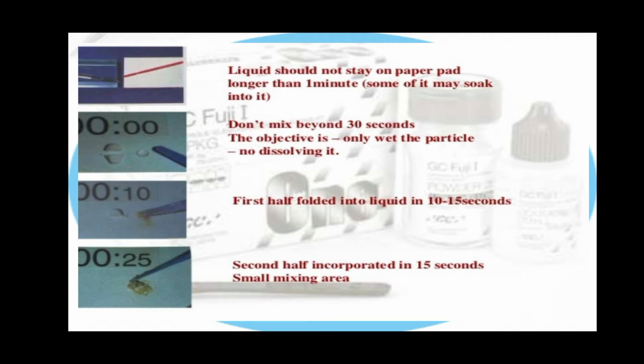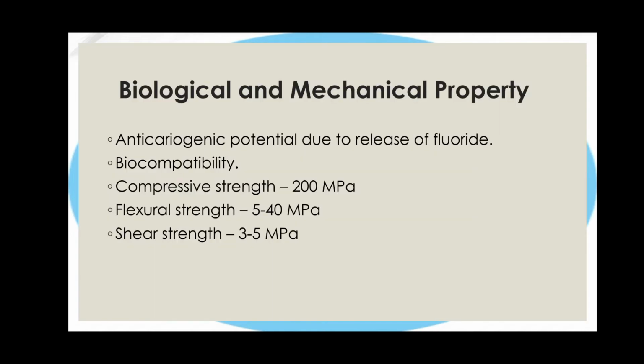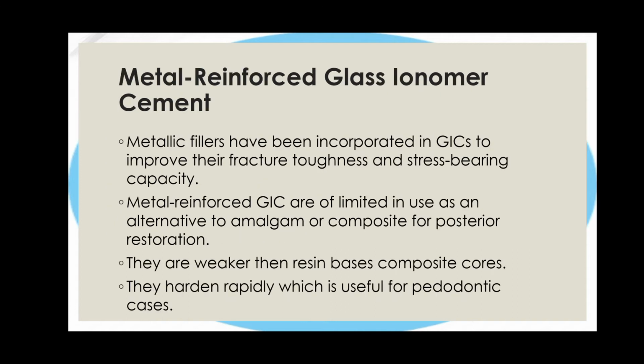The objective is to wet only the particles, not dissolving them. First half is folded into liquid in 10 to 15 seconds and second half incorporated in 15 seconds. Small mixing area. This is the mixing of GIC. And biological and mechanical property of GIC: anticariogenic potential due to release of fluoride, biocompatibility, compressive strength 200 megapascal, flexural strength 5 to 40 megapascal, shear strength 3 to 5 megapascal.